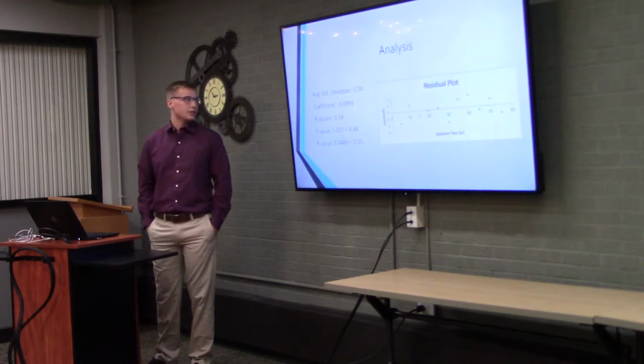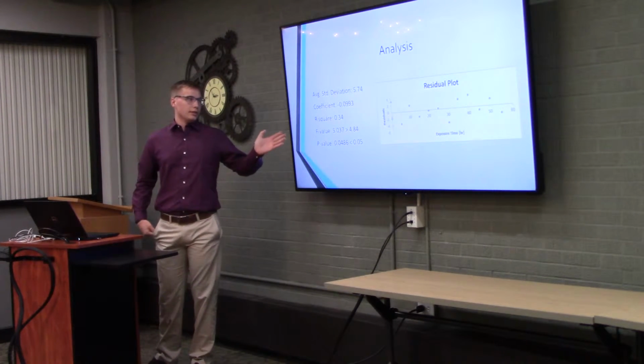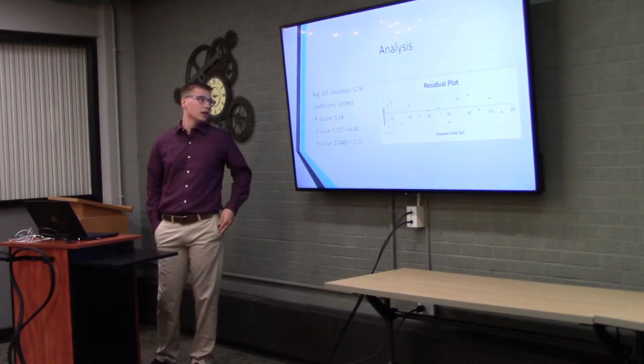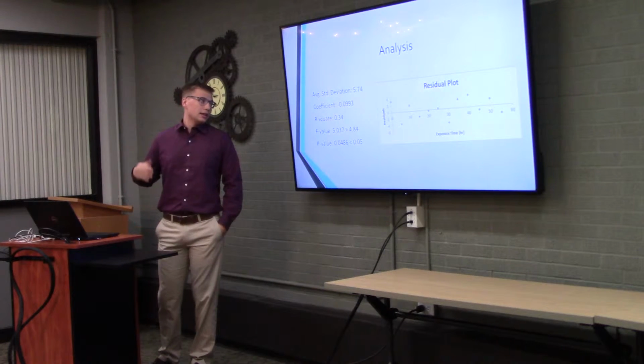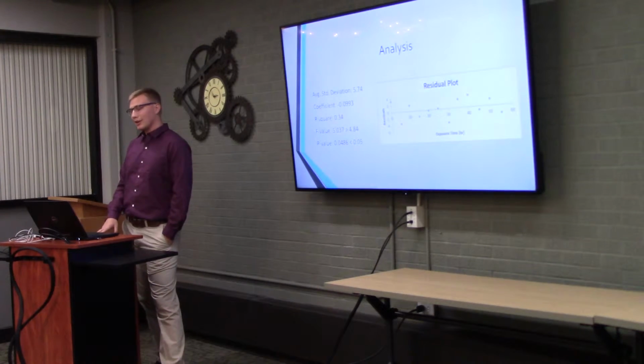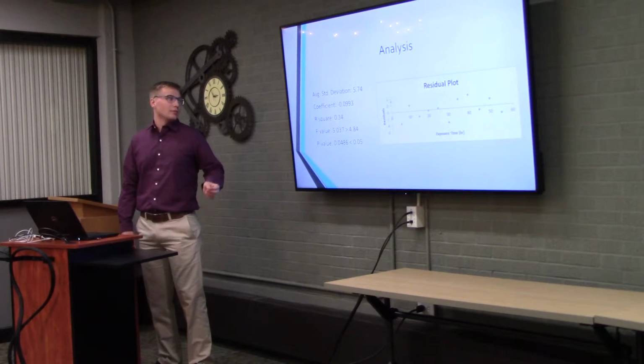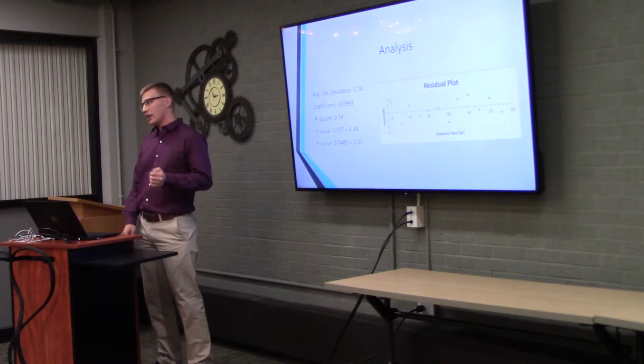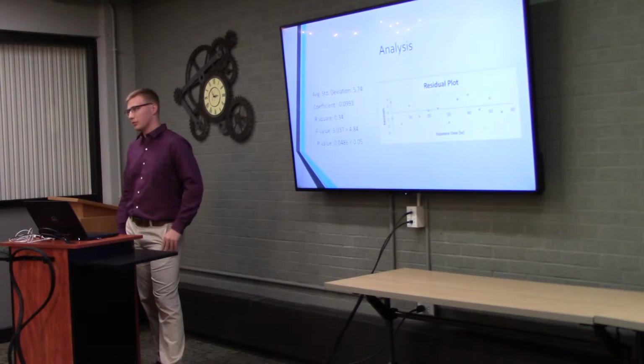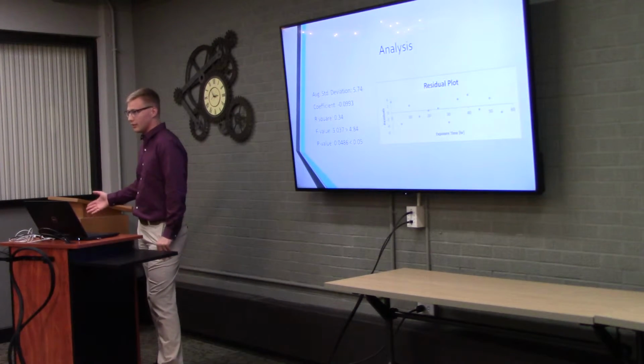That's the average standard deviation we just talked about. This coefficient is what the model showed is how much the hardness is decreasing per hour. So it indicates that the hardness decreases at 0.0993 per hour on the Rockwell hardness scale. The R-squared value means that 34% of the variation in the hardness data that we saw was due to the amount of time that it was submerged in the FLiNaK, which obviously isn't ideal. You want to see 100% ideally, but it is significant.